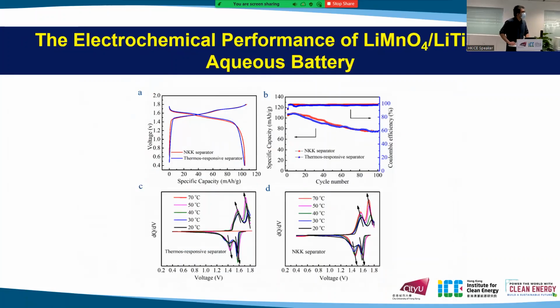For the battery, we use LMO and LTP as cathode and anode, because LMO has a three-dimensional lithium diffusion path, and LTP has a NASICON structure, which is suitable for fast charge and discharge. And the most important thing is that the voltage working window is suitable, and the electrolyte is suitable for this system. From the charge-discharge curve and the cyclic performance, we know that there's not much difference when tested at room temperature.